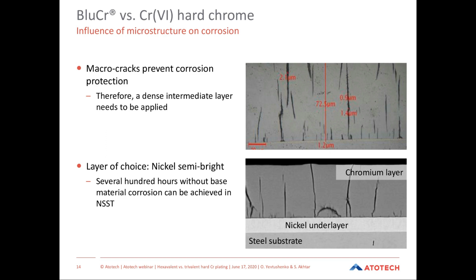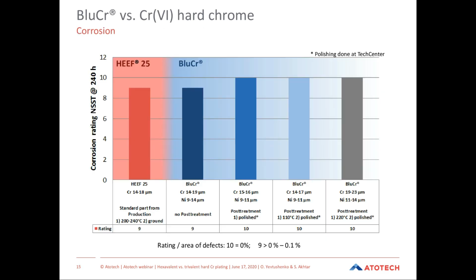Therefore, to avoid this, we need a dense intermediate layer in between steel, the substrate, and the chromium. And this layer will provide necessary corrosion resistance. So the layer of choice might be semi-bright nickel. Semi-bright nickel has high corrosion resistance itself, at least in case of neutral salt spray testing, which is also commonly used for our application. And using this nickel underlayer, you can easily achieve several hundred hours without base material corrosion.